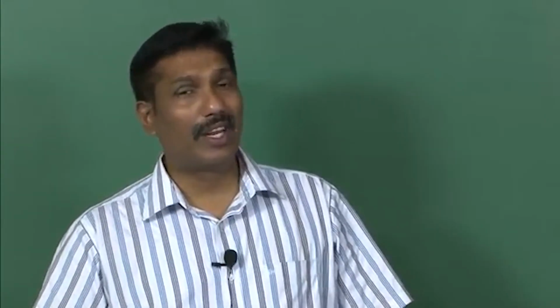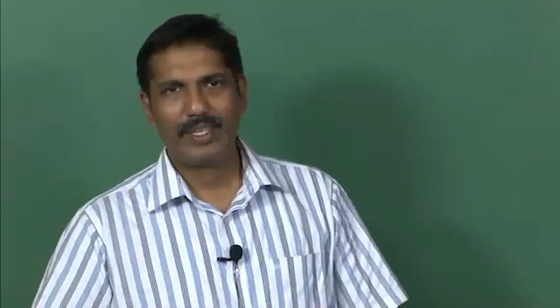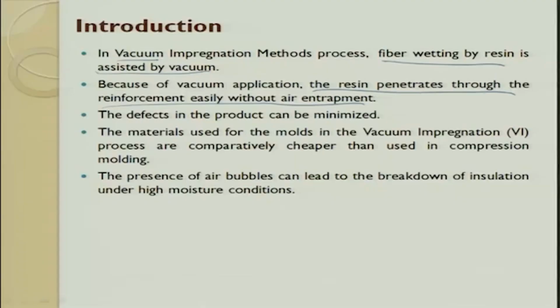Suppose you have multiple layers and an air bubble is stuck in between, then you will never get a sound quality output. So, in order to avoid this, we put the fiber mat and then we suck air. When you suck air, the possibility of air getting trapped is less. That is why we always go for vacuum assistance while pouring the resin. So, the defects of the products are minimized, and the vacuum impregnation process is comparatively cheaper than the compression molding process.